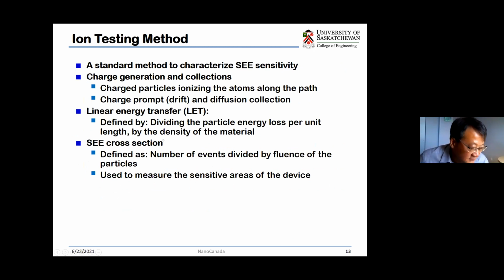Okay, so in this field, once we have some electronics for space or even for ground level, we always need to figure out how to test them, right? And the standard way is that we use ions to do the testing. When we use ions, we have one way to measure the energy deposited into the device. We use linear energy transfer. Basically, we divide the particle energy loss per unit length by the density of the material. So that's a way to measure how much energy we deposit into the material. And once we have that, we have the SEE cross-section. Basically, we define it as the number of events divided by the fluence of the particles. We use this to measure the sensitive area of the device.